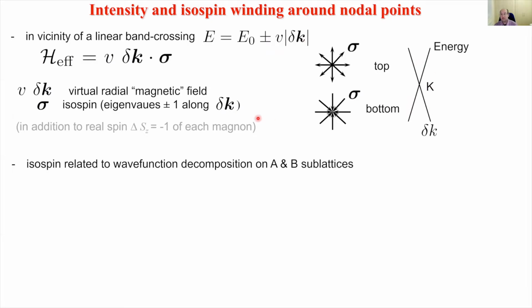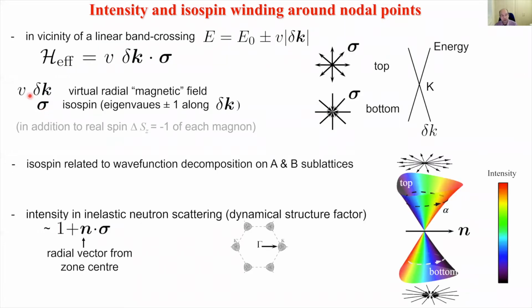So this isospin is, of course, a property that is separate from the real spin of the magnon, because all magnons have delta Sz minus 1. This isospin is really related to the wave function decomposition on the two A and B sublattices of the honeycomb. So one can see direct evidence of this isospin in the fact that the intensity in inelastic neutron scattering, which is the dynamical structure factor, is related to the projection of the isospin onto a characteristic vector n, which for the case of the first Brillouin zone is the vector that's radially out from the gamma point.